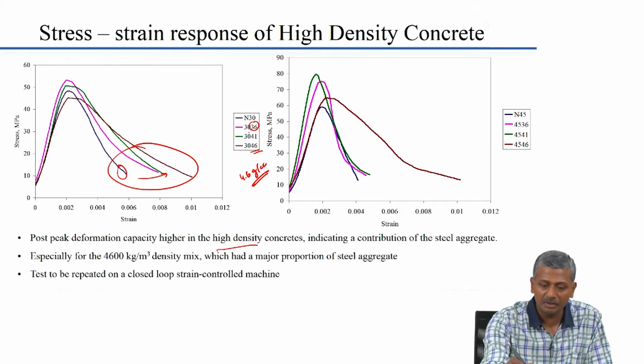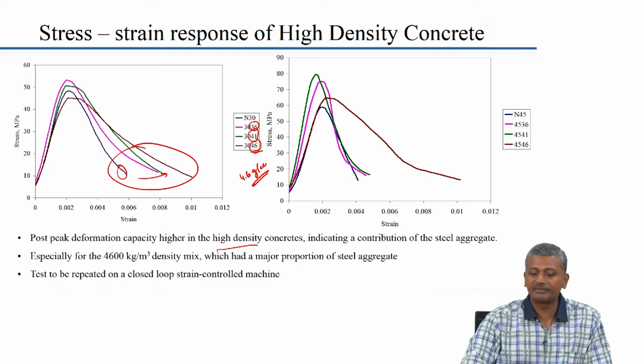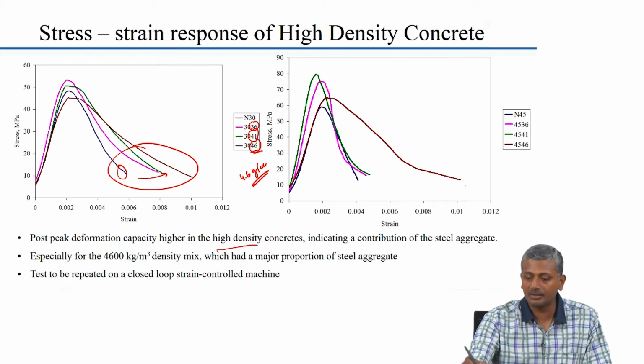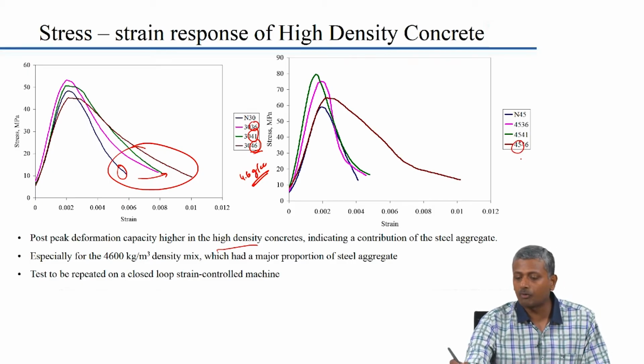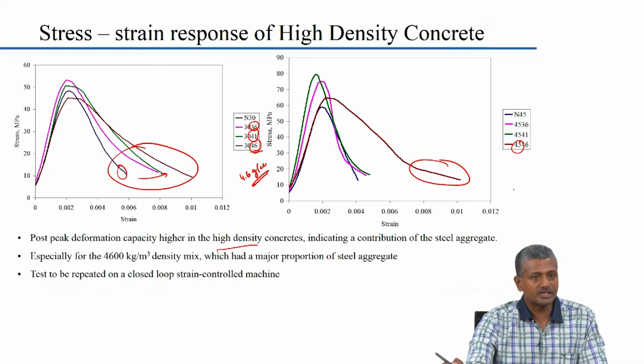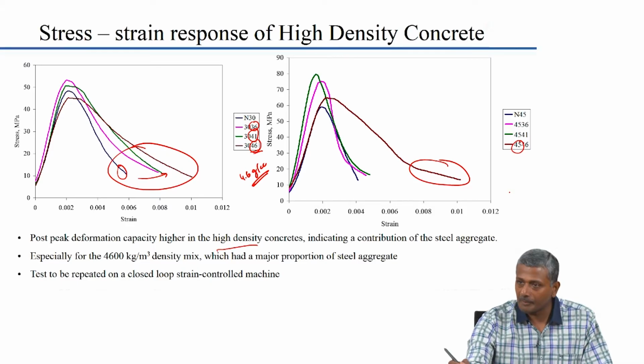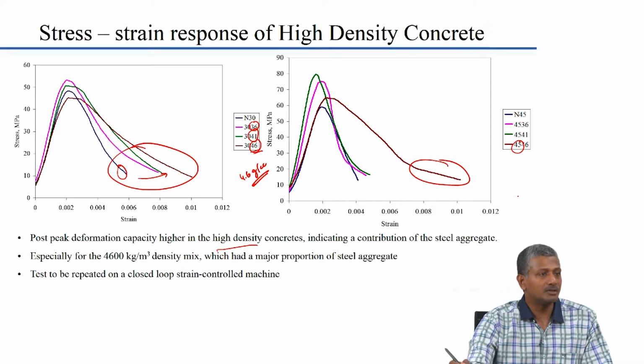3.6 grams per cubic centimeter, 4.1, and that is 4.6 grams per cubic centimeter. As you can see in the higher grade concrete, that is M45 grade concrete, that there is sufficient deformation that we actually were able to obtain with the 4546 mix that corresponds to the 45 megapascal concrete, which is achieving 4.6 gram per cc as the density.